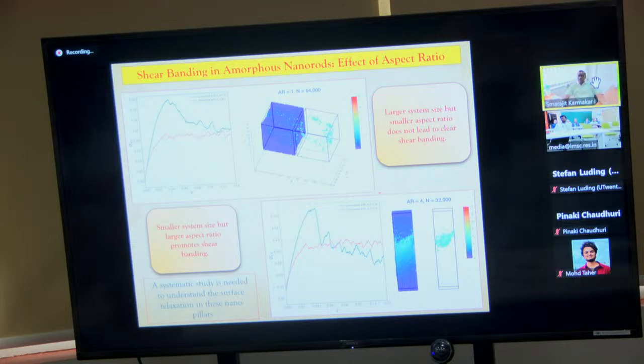So this tells us that with a smaller aspect ratio, you are going to get less shear band formation, but a smaller sample with an elongated geometry will have much more shear banding. That's why, when pillars are used for any practical purposes, one has to be careful about stability, because they can fail catastrophically as well. Maybe I stop here. I had a couple of slides on memory formation, but I'll skip that part because it requires some discussion as well.